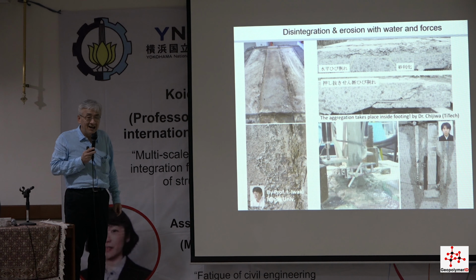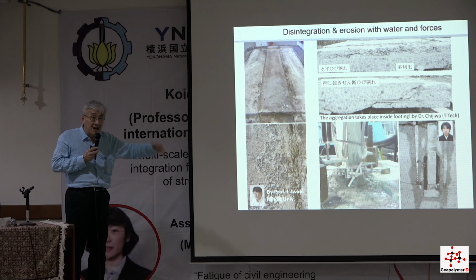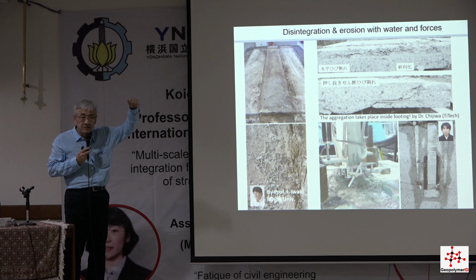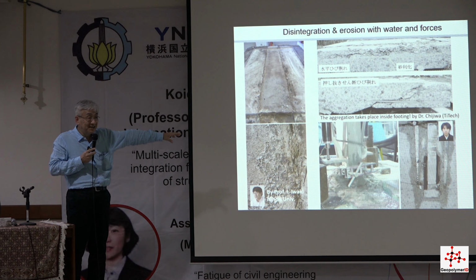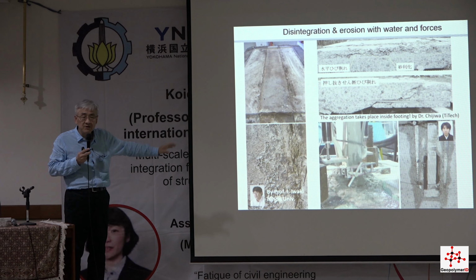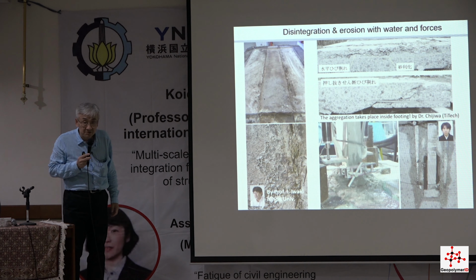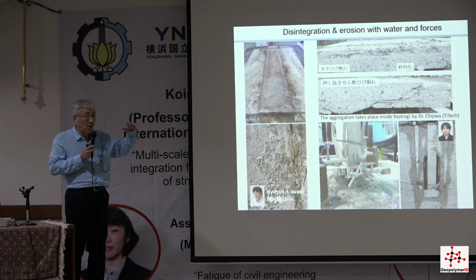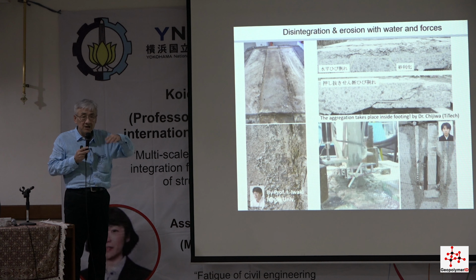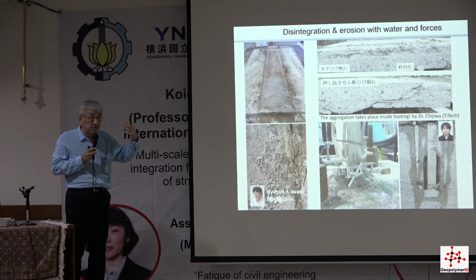However, one of the reasons is that water is coming here, we apply the load, and we check the pressure inside. Pressure level is around 1 or 2 megapascals. Almost the same level as tap water. At the same time, 1 or 2 megapascals is also similar to the tensile strength of concrete.